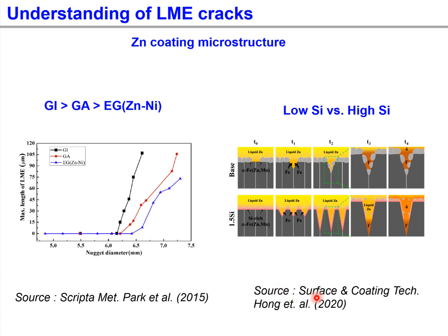Hong et al. also found that silicon in the steel delayed the dissolution of the iron into the coating from the steel, which suppressed active formation of the alpha Fe-zinc layer. Then it could not prevent the steels from contacting liquid zinc during the welding. So there is an underlying mechanism of the effect of zinc coating microstructure on the LME crack occurrence.